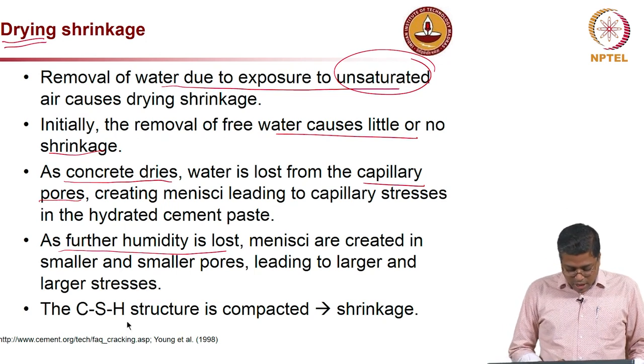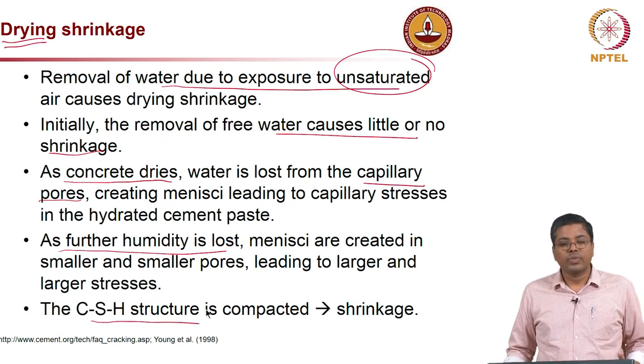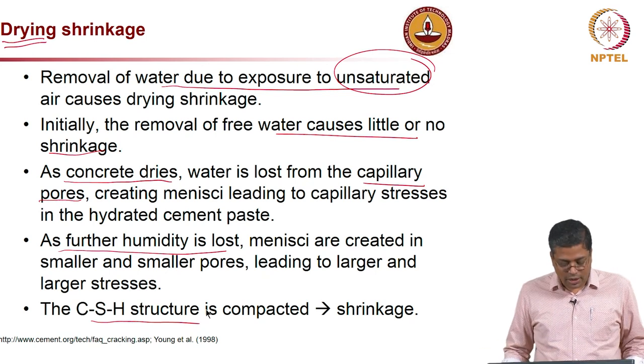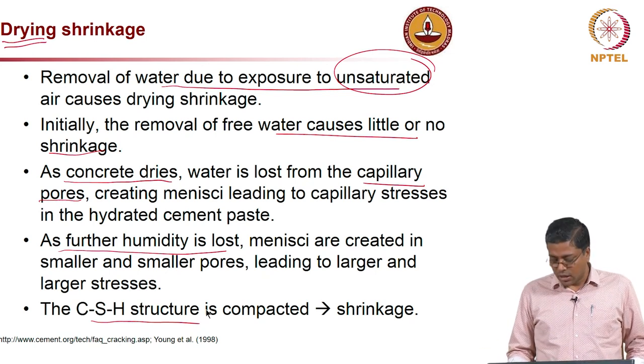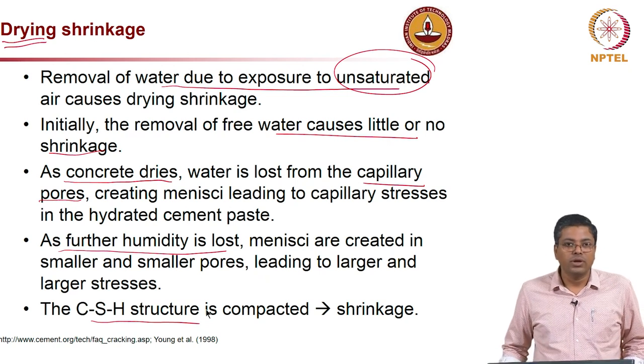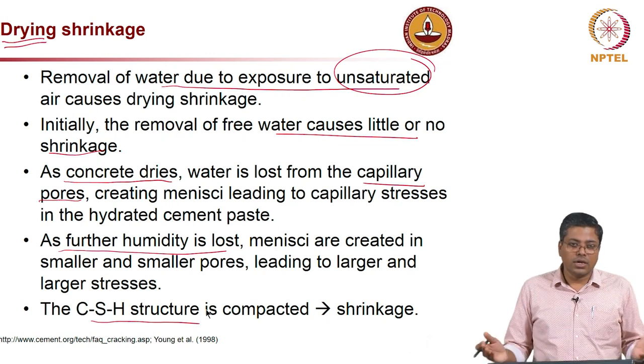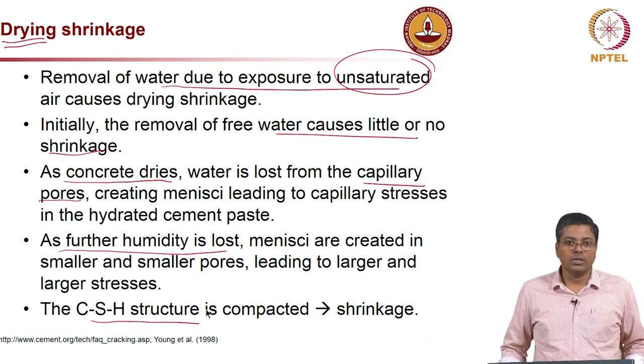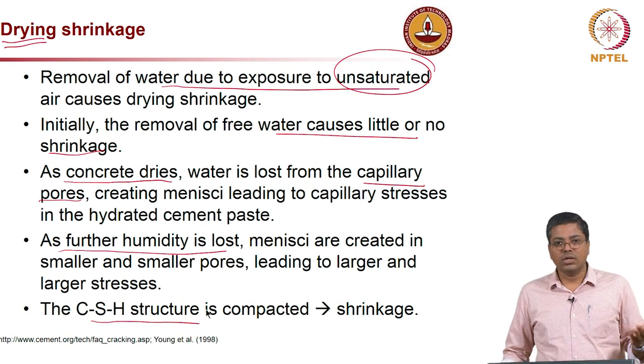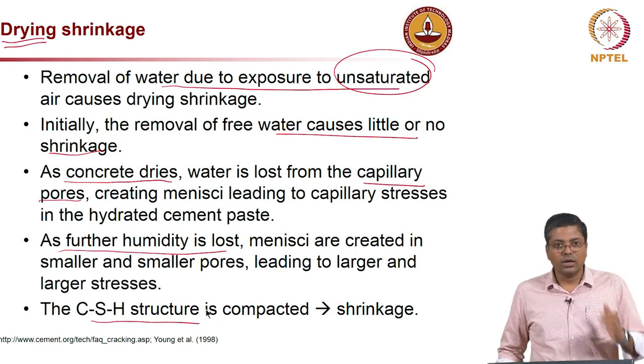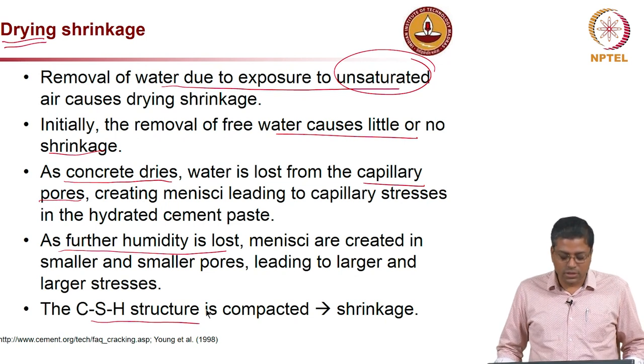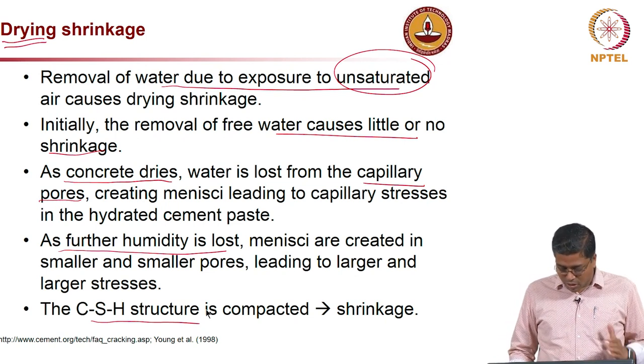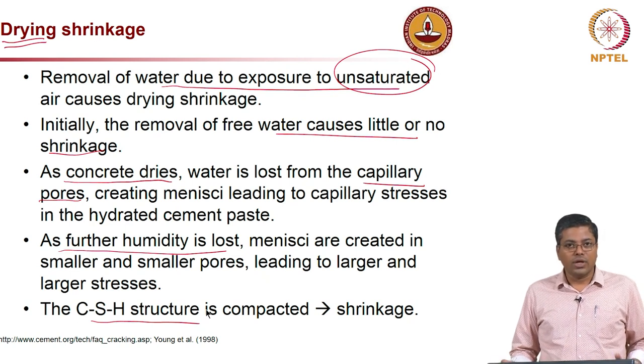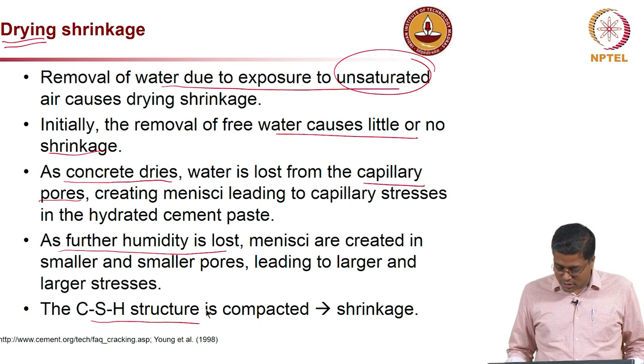And also this CSH structure eventually gets compacted, that means the entire concrete system tends to shrink, which will lead to cracking because of the presence of aggregates and other restraints which are provided by either the steel reinforcement or the surrounding earth, or whatever the concrete is in contact with. So, as long as there are restraints, this could lead to cracking. If there is no restraint, this could just lead to shrinkage.